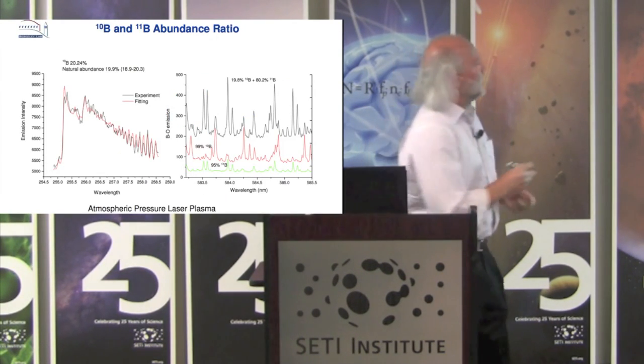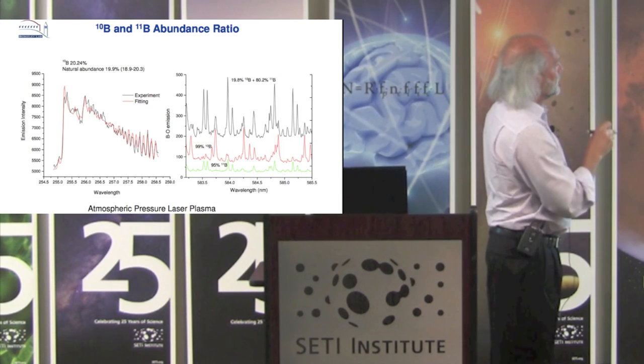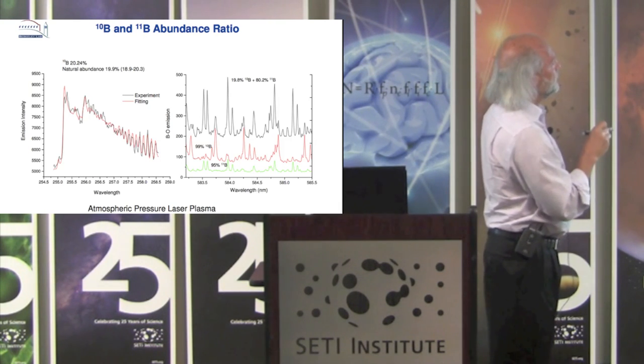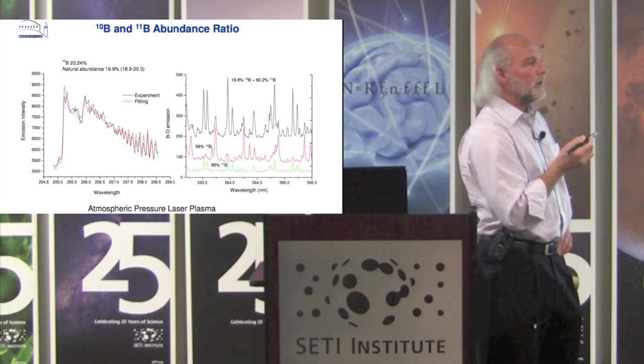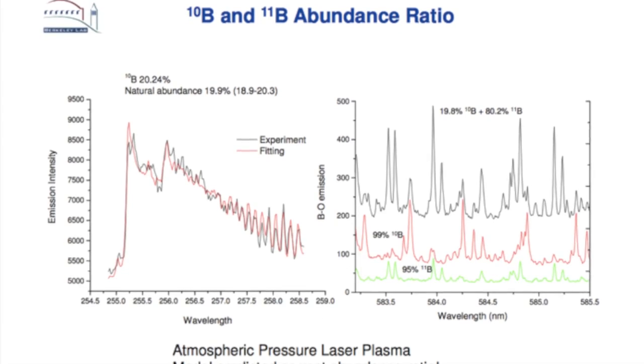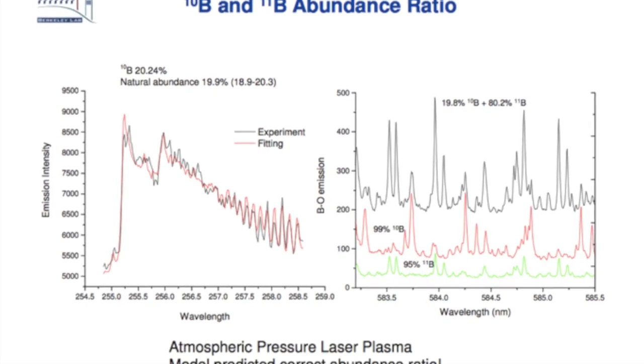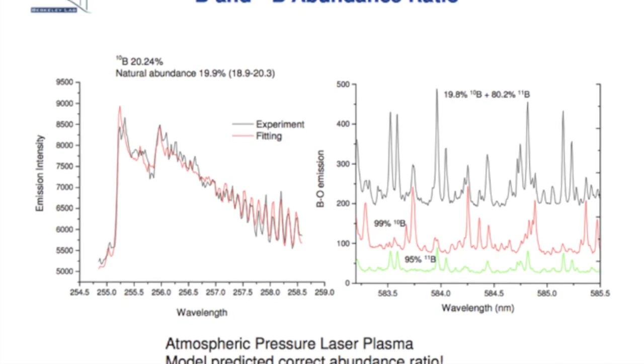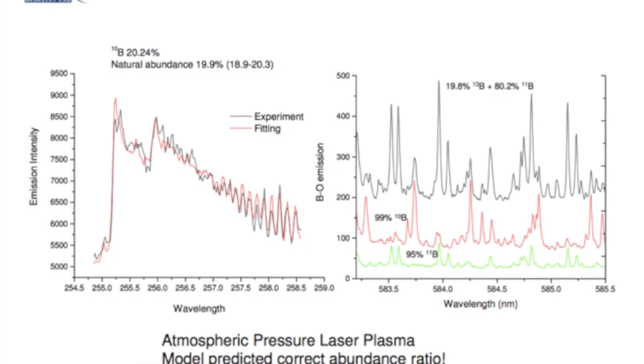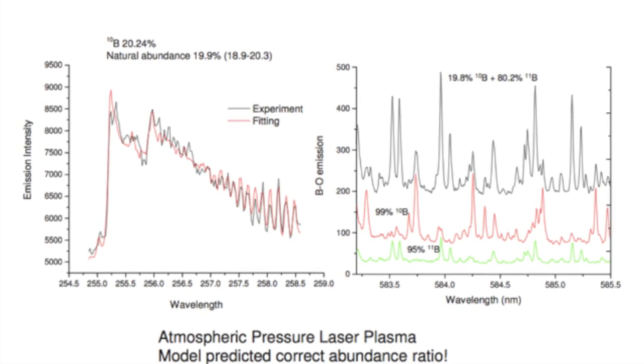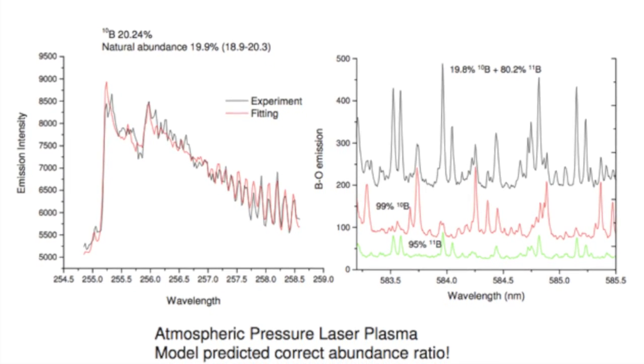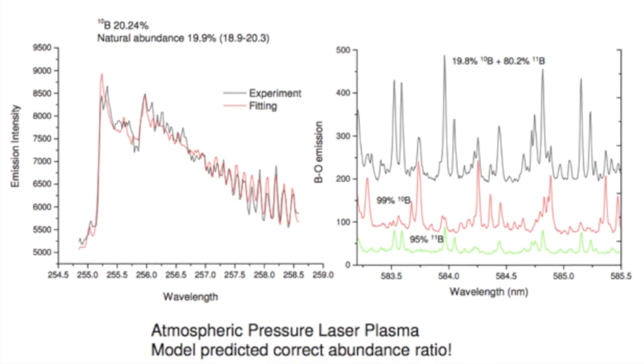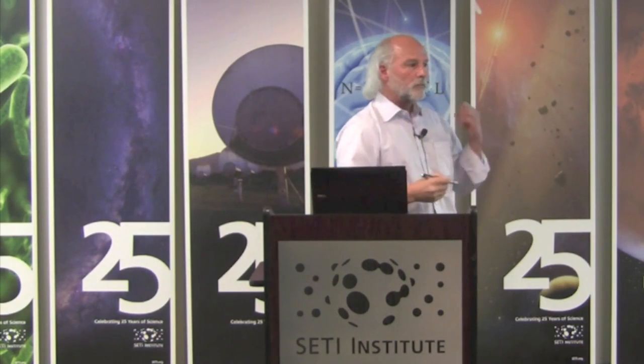Okay? We can actually calculate what the spectra should look like, and we can fit that using fitting parameters to calculate what the isotope ratio is. And you can see, even though our model is not perfect, we don't fit the spectra perfectly, we do calculate the right abundance ratio. We calculate that the boron-10 abundance is about 20.24, and if you look in the literature, you see it's anywhere from about 18.9 to 20.3. So for one single laser shot, the fact that we can do this at atmospheric pressure, no sample preparation, just immediately get the measurement, that's pretty spectacular.